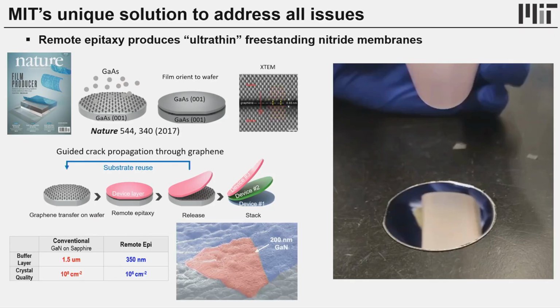Okay, so we believe if you know how to make high EQE, high efficiency micro LEDs in an ultra thin, freestanding form, then it's going to be the solution. So now my lab at MIT has been developing a way to make micro LEDs ultra thin. You're looking at perfect single crystalline gallium nitride coated on a human skin replica. It's that thin, 200 nanometer perfect single crystalline gallium nitride on the human skin replica. It's super thin. This is enabled by a technique called remote epitaxy. I don't have time to go over the whole physics around this, but we know how to grow perfect single crystalline LEDs on graphene on the wafer.